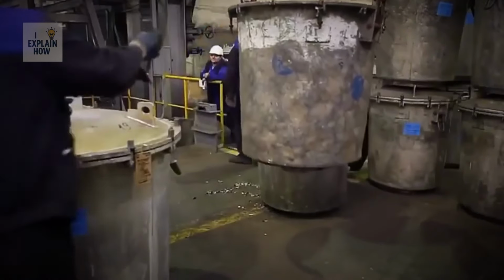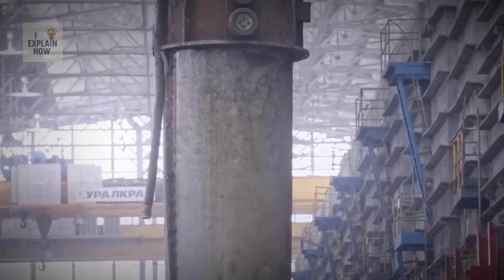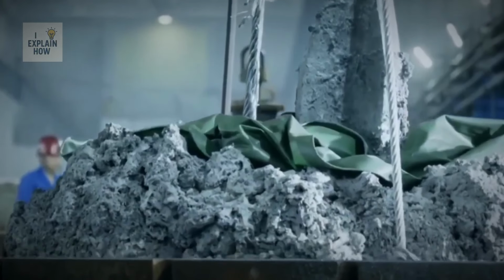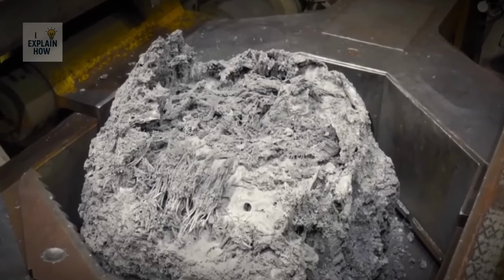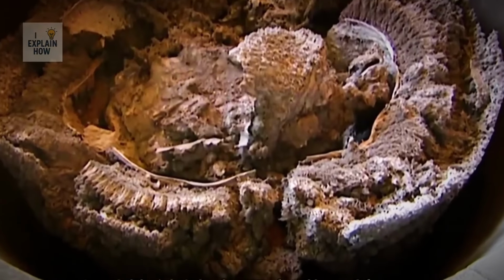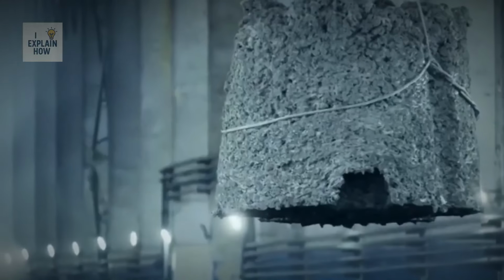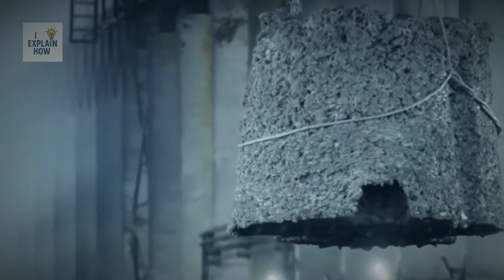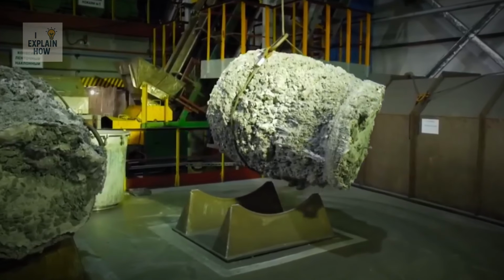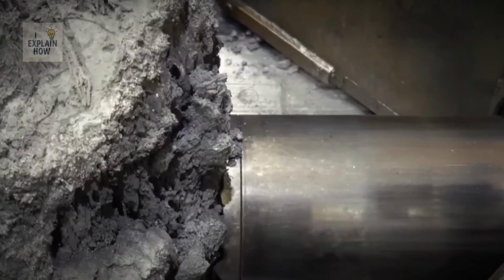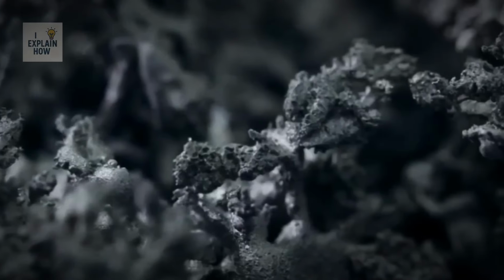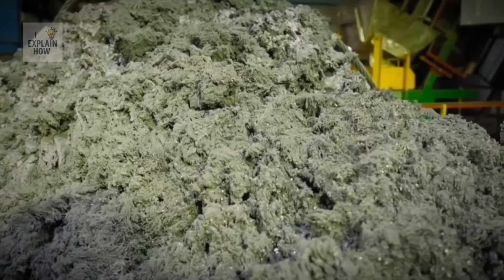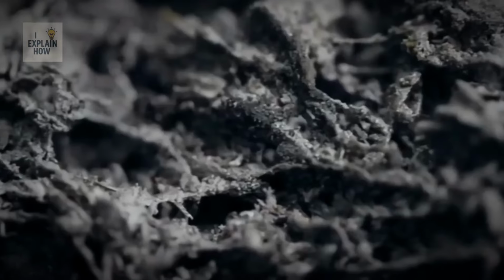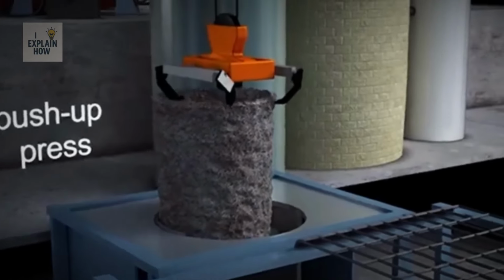Then comes the magic moment. Molten magnesium, an even more reactive metal, is introduced. A veritable atomic battle ensues. The magnesium strips away the chlorine atoms, thus releasing pure titanium. It's a chemical dance where one metal sacrifices itself to free another. For hours, titanium slowly deposits on the cold walls of the reactor. When the process is complete, what emerges is not a shiny ingot, but a gray, porous, and surprisingly light mass, resembling a sponge or a piece of coral. This metal is titanium sponge, rough, fragile, and full of cavities.